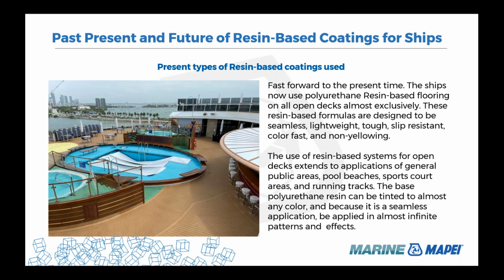Now we fast forward to the present time. The ships now use polyurethane resin-based flooring on all open decks, and this is done almost exclusively. You're not seeing much of the wood teak any longer. The use of resin-based systems for open decks extends to applications for your general public areas, your pool beaches, sports court areas, running tracks, children's play areas. The base polyurethane resin can be tinted to almost any color, and because it's a seamless application applied in almost infinite patterns and effects, it's designed to be lightweight, tough, slip resistant, color fast, and non-yellowing.